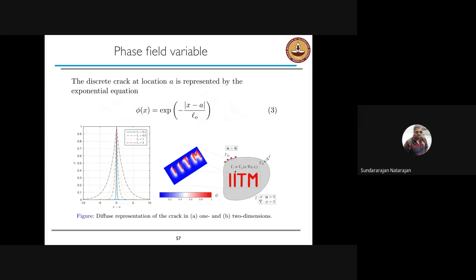So the basic idea in phase field is that the crack can be represented or thought of as two different phases. The region where there is no crack, we call that an undamaged state. And there is a region where there is a crack, which is a damaged state. The transition between the damaged state and undamaged state is what we call the phase field variable. And typically it takes a value of 0 to 1. So 0 implies it's undamaged, 1 it is completely damaged.